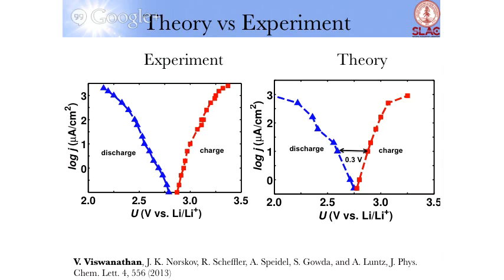There are also some other nice features that you can see. There's this nonlinearity that we observe. This nonlinearity essentially comes from a transition from growth on a step site to a terrace site. I told you earlier that terrace sites had a large overpotential, and so in order to transition from the step site to the terrace site, you have to pay a higher penalty, and that penalty is a lot less during charge. You in fact even see those features in the experiments where you see a much broader what's called a Tafel slope, which is essentially the slope of this line. You have much worse chemistry under discharge than charge.